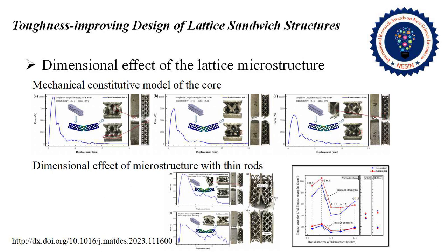For the core with thick rods, the impact toughness of the microstructure samples decreased with decreasing rod diameter. This is because, according to the fracture criterion, when the stress at the front of the crack decreases with the reduction of rod diameter, the strength factor decreases as well. This causes the fracture toughness of the core to decrease. Similarly, the energy absorption efficiency by deformation of the microstructure core also decreases with decreasing rod diameter. Therefore, the impact toughness of the samples decreases dramatically when the rod diameter decreases.